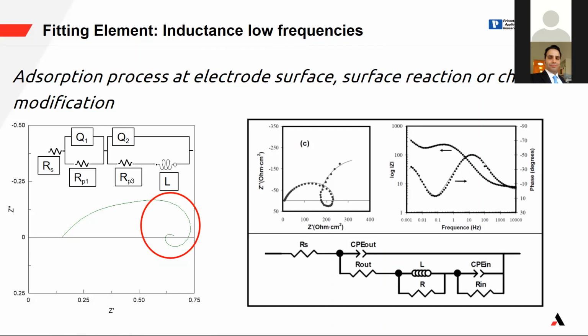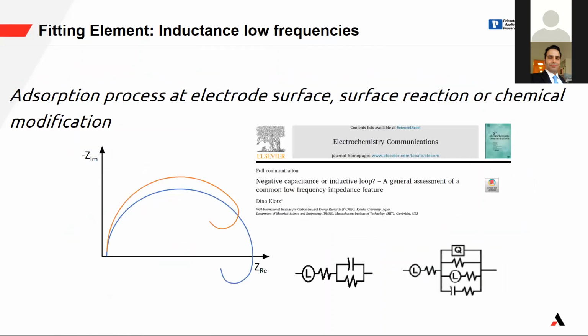This is typical in fuel cells, but sometimes you can also see it in corrosion, and in other experiments. For example, if you analyze nickel in corrosion, you will see a huge amount of this variation, because nickel is passivating during the measurements. For example, in some articles, nickel is passing from nickel 2 to nickel 4, and this modification gives this variation in the resistance.